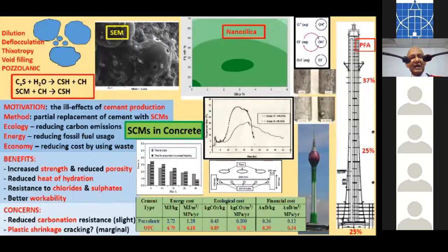Now, where fly ash is concerned, there are some concerns. There is some reduced carbonation resistance, but this is very, very small. And one of the things that we need to do with fly ash concretes is perhaps to make sure that they are cured better. And also there can be some plastic shrinkage cracking because of the closed structure of the fly ash concrete. The bleeding is reduced, and so the time for the evaporation to exceed bleeding will reduce with the increase in pulverized fuel ash. This is another experimental setup that we had at Moratuwa University, and these tests were done many years ago.